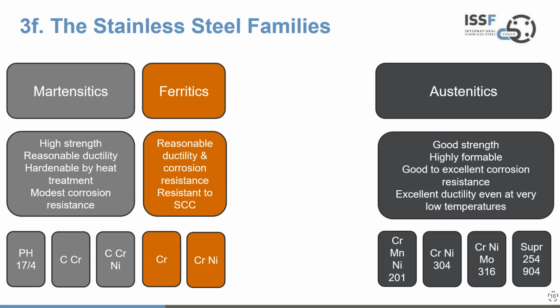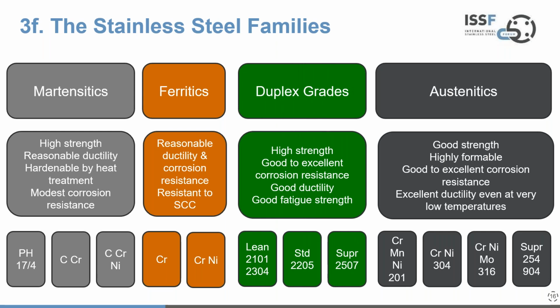And this is where people are familiar with the 18-8s and the 18-10s and all the associated products in this family. Sitting between ferritics and austenitics is the new kid on the block, so to speak, even at 90, still the new kid on the block in many people's heads. This is a combination of the ferritic body-centered cubic structure and the austenitic face-centered cubic structure. So you've got a blend of these two structures, which gives high strength, good to absolutely excellent corrosion resistance, but not losing so much on ductility, good fatigue strength. And here you have the classic duplex grades with 2205 being the most common. And then we've gone leaner in more recent times and also into the super duplexes, 2507. So that's the whole stainless family.